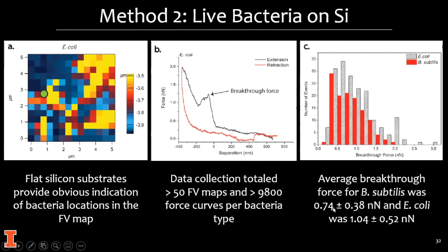One thing I want to point out is that the breakthrough force of these membranes is 1 nanonewton or less. Especially if you're just trying to image topography, you really need to pay attention to the amount of force that you're imaging with, because you don't want to deform the topography or shred the bacteria. You want to actually image it, so you're going to need to keep the force much lower than this. Okay, so this is just looking at one aspect of these soft materials, which is the breakthrough force, which is unique to looking at membranes.